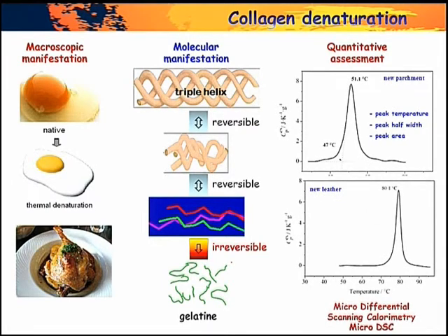Okay, one of the best ways to assess this process is differential scanning calorimetry. This is a technique used for assessing protein denaturation, and the advantage of such a technique is that we obtain not only qualitative but especially quantitative information. So in few words, in a calorimeter, a sample is heated at a constant rate, and when denaturation, thermal denaturation in this case, which is induced by heating, occurs, a peak is registered. And the features of this peak are directly related to the quality of the protein in the material analyzed.